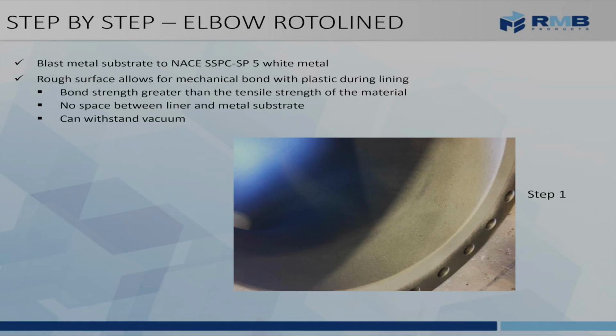So just taking an elbow, for instance, we're going to blast the inside surface, including onto the face, to the SSPC SP5 white metal. And this rough surface is going to be about a 3 to 5 mil depth surface profile. What this does is that when the resin is then inserted and bonded, we get a vacuum rating. We actually have that strong of a mechanical bond with many of the resins that it can be a full vacuum rated part. And there's no annular space whatsoever between the resin and the steel.